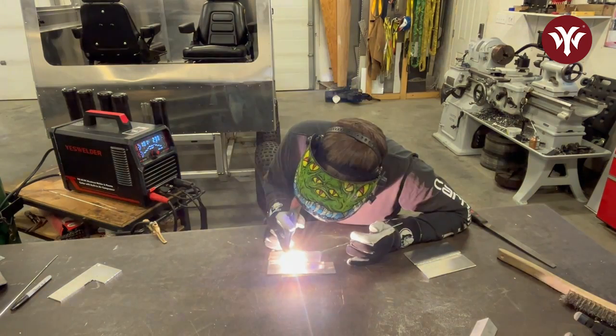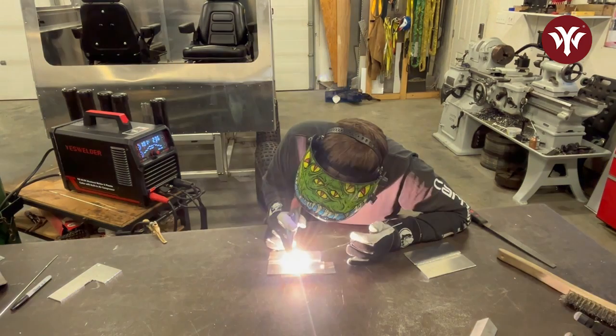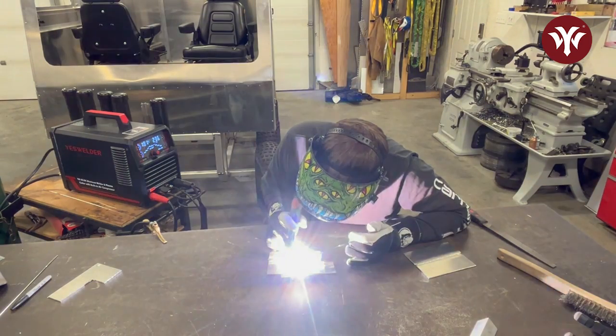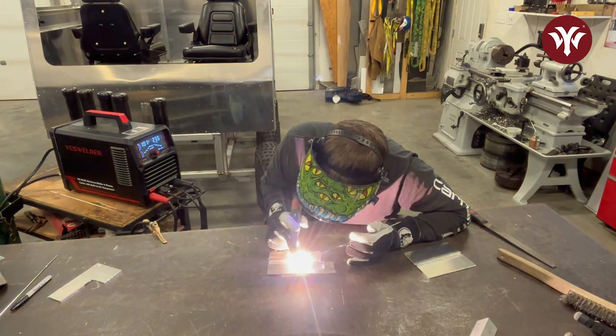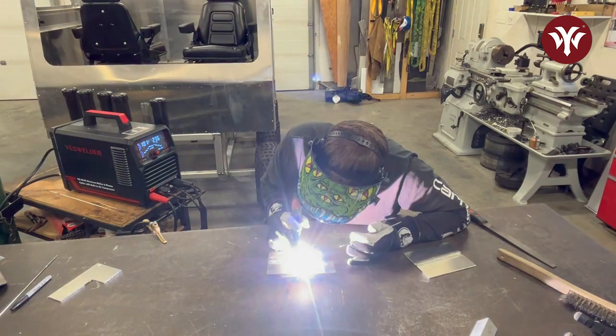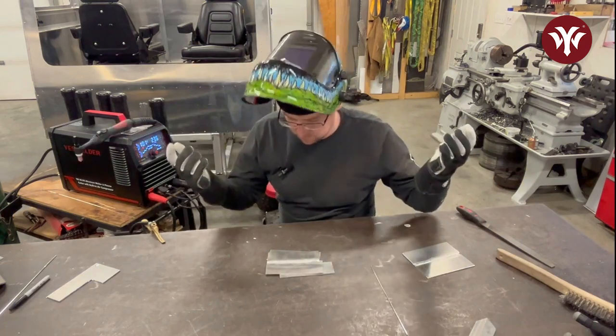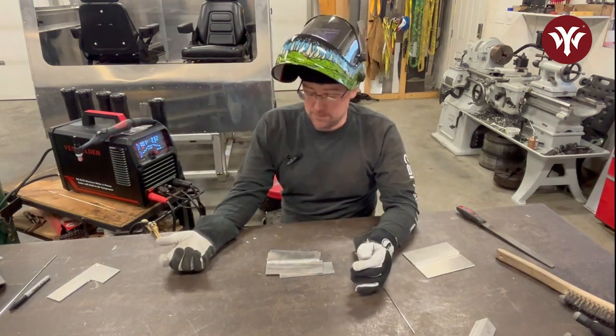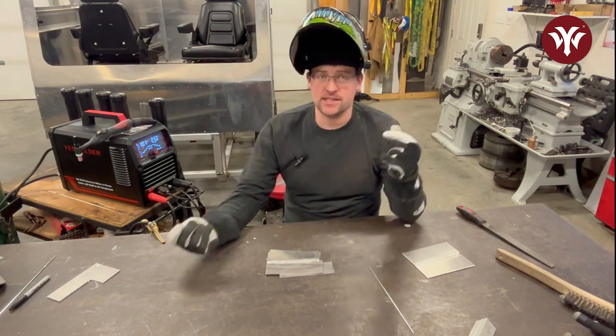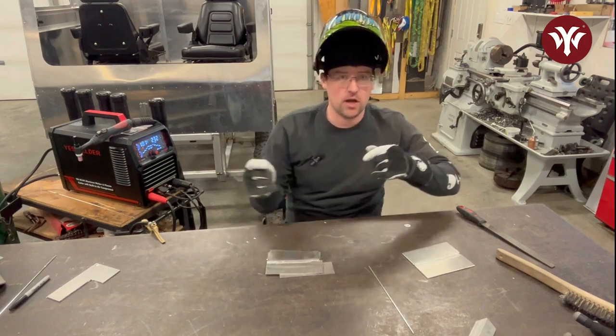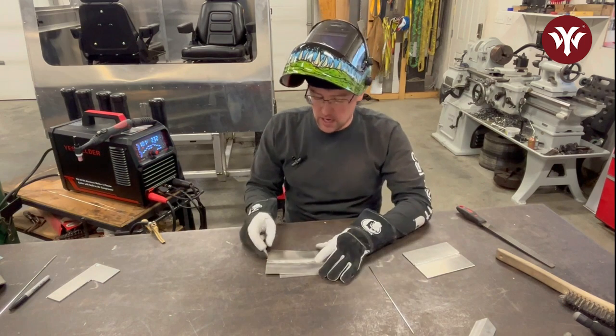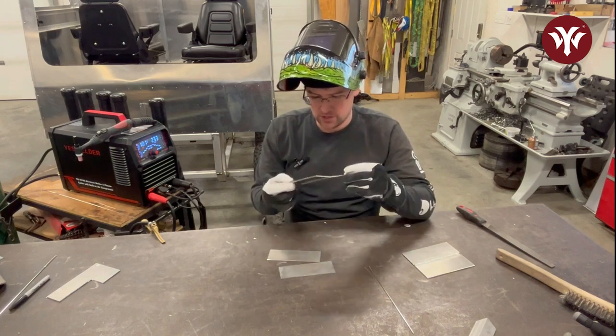I'd like to make a comment here that hertz is pulses per second. It's just another way of explaining it. So at 0.5, you're dealing with 1 pulse every 2 seconds or half a pulse a second. And at 1 hertz, it would be a pulse every second. So right now I am running at 0.8 pulses a second. That's pretty good. That definitely picked up the pace for me. It sets the tone to move the torch, feed the rod, move the torch, feed the rod. I probably couldn't go much faster than that.